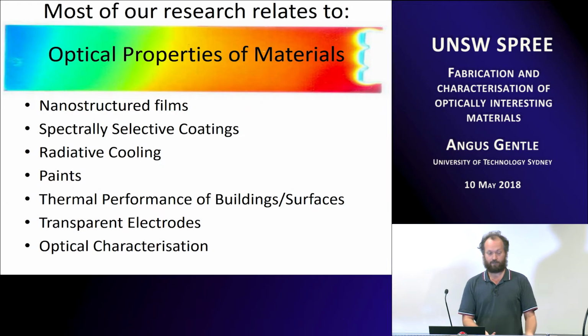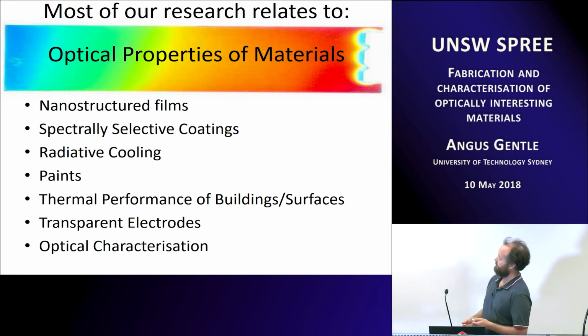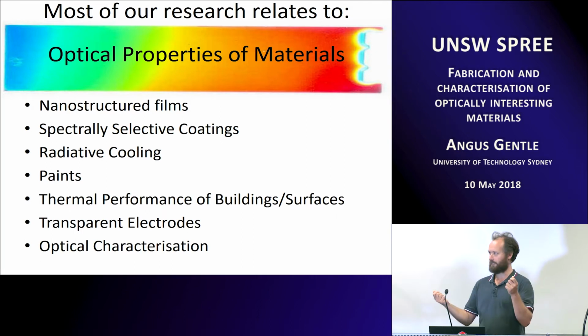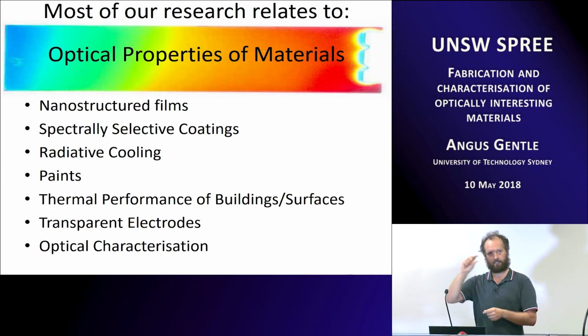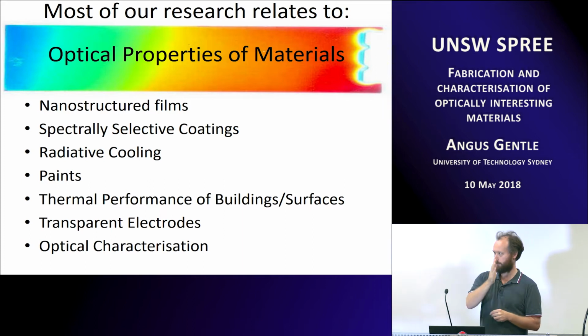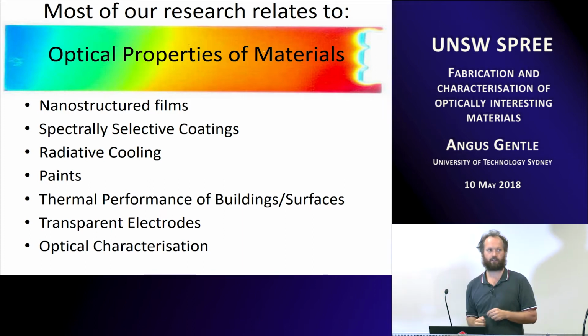So most of our research is optical properties of materials, whether we're characterizing someone else's material, making your own material from scratch, or getting a material that people haven't actually looked at much before. So that pretty picture at the top is actually a slide that we made. It's made up of 5 layers of silver, alumina and silver, and it's tapered thickness of the alumina. So it ends up being a resonant cavity between it, so you can transmit, so it's put on a scanner and that's the transmission going through at different ends.